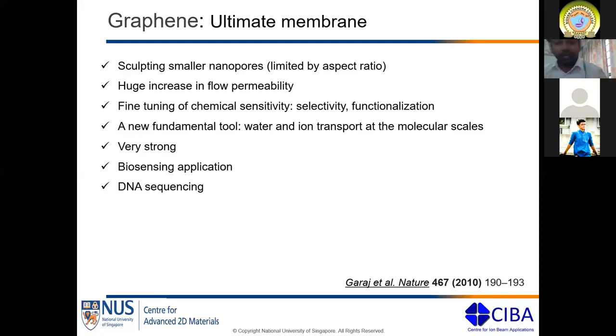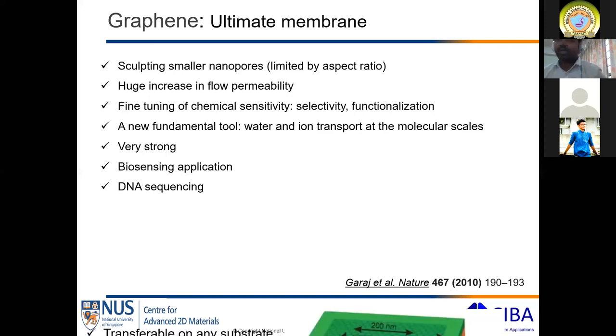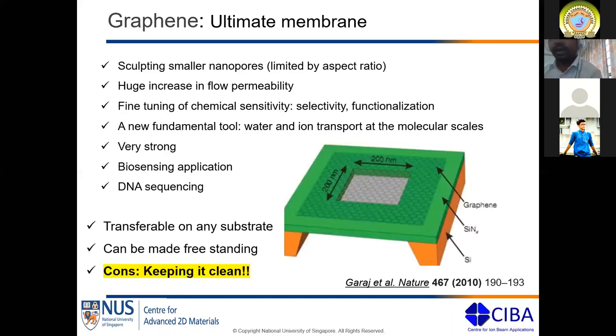What I use here is based on this kind of freestanding on-chip setup, basically chips we use to give support to the graphene membrane. You can see the silicon nitride membrane is supported by a silicon substrate, and on top of it you transfer graphene. The beauty of graphene is that you can transfer it on any substrate if you want, and then you can make it freestanding as well. It can be supported or it can be freestanding.